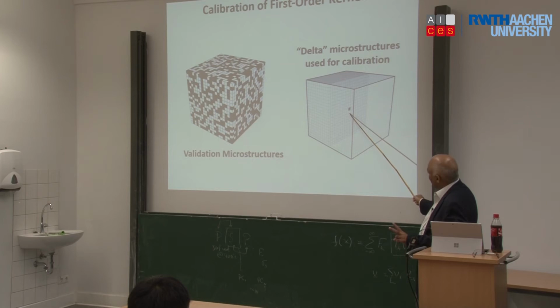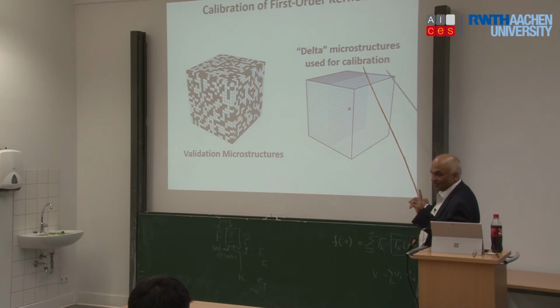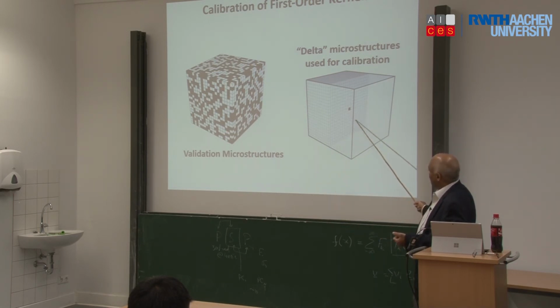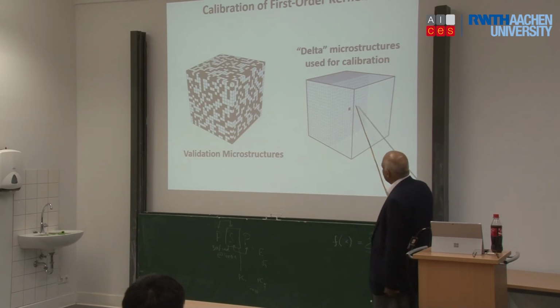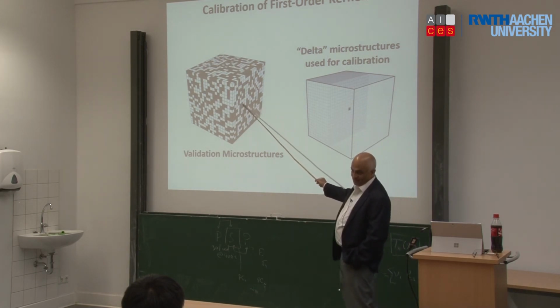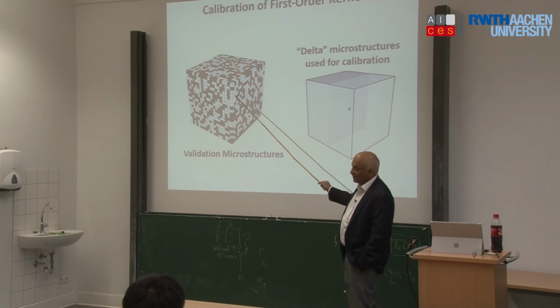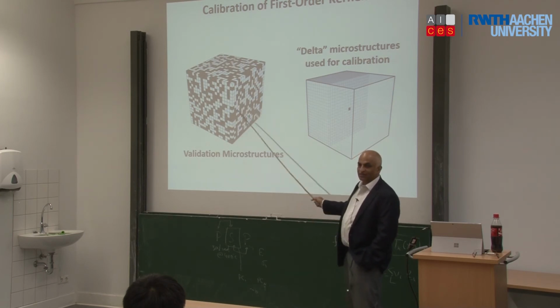So, if I have a 2-phase material, I have a black phase surrounded by white, that's one material, one data point. Then I have white in the center surrounded by black. So, I use only 2 microstructures, and then we run finite element simulations on this. I get my Green's functions, or the kernels, Green's function based kernels. Once I have the kernel, I'm saying you make up anything you want. For example, this is you make up anything you want, and then I'll predict it for this.